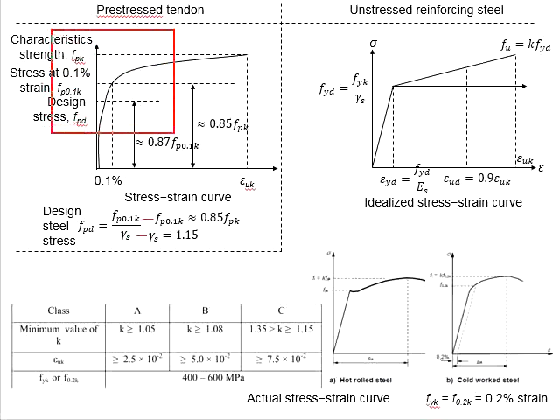This can be graphically represented by the diagram here. This is the characteristic strength of the prestressing tendon. The specified yield strength is about 85% of its ultimate strength. It is basically obtained from the offset gradient of 0.1% strain. And when it comes to the design stress, the specified yield strength is divided by the partial factor of safety for the steel, which results in 87% of its specified yield strength. That gives a tolerance of more than probably 20% to the ultimate failure of the tendon.